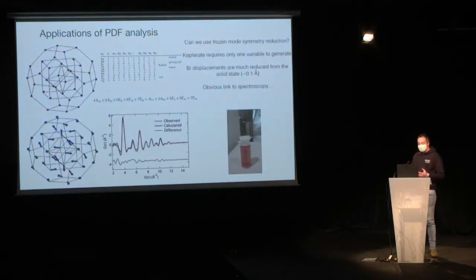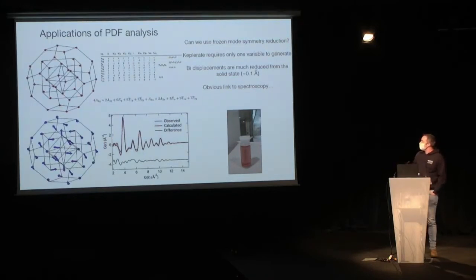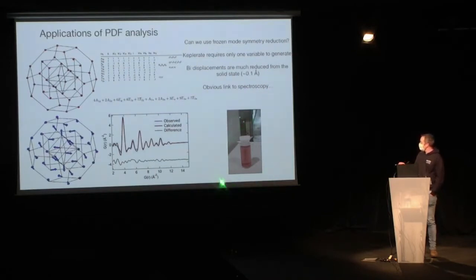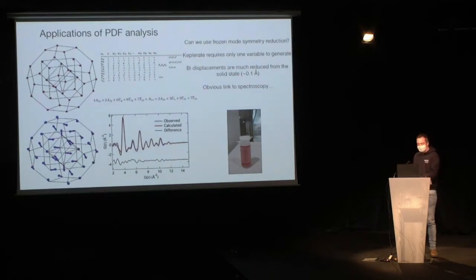We think that's the reason these clusters are transiently stable at rather high energy — they're not able to distort because they don't have the interaction potential from forming a crystal. The same can be done for larger clusters. One can use this so-called frozen mode symmetry reduction to parameterize the larger Bi38 species and show that its displacements are much reduced in the solution phase compared to the solid state. What we're currently working on is linking this to spectroscopy — doing MD simulations and DFT calculations to explain the vibrational and electronic spectra of these things in solution, which is important for their properties.